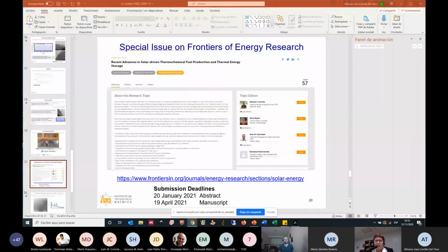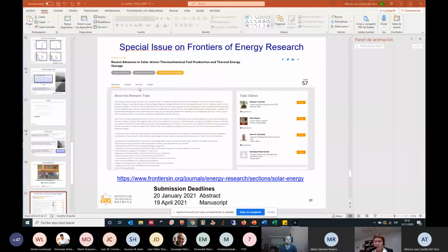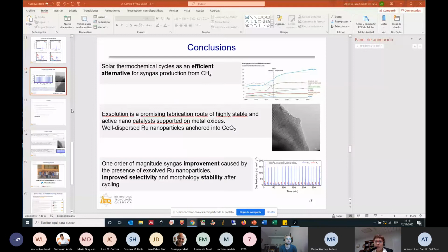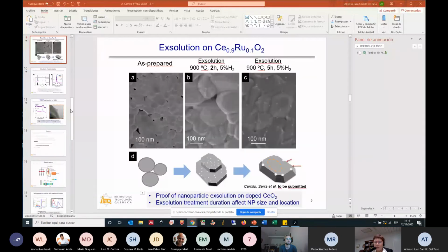The first question is, with time, the nanoparticles appear to be bigger and located on the grain boundaries. So how can you exclude that they have not dissolved on the surface and then migrated to the grain boundaries and agglomerated later on?